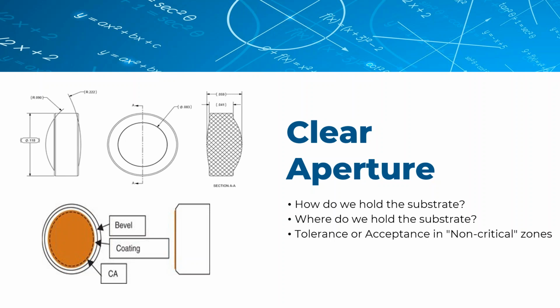So when our customers specify the clear aperture of the part, what they're basically telling us is where we can hold it and what surface absolutely cannot be interrupted with a tooling mark. Here I have a simple biconvex lens with a nice bevel all around the outside. You can see the orange area is where I'll be coating. The dashed line is the clear aperture, and it's understood that anywhere outside of the clear aperture is acceptable for me to hold on to. So that's how we talk about clear aperture and holder allowance. It's called tooling mark allowance. Those are some of the different ways it's specified.